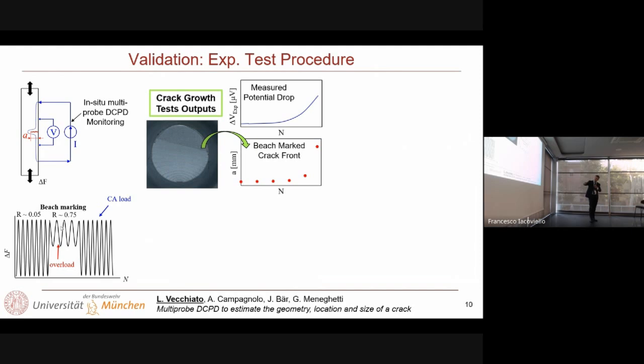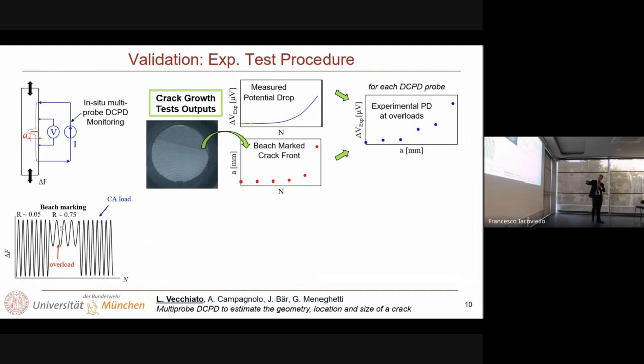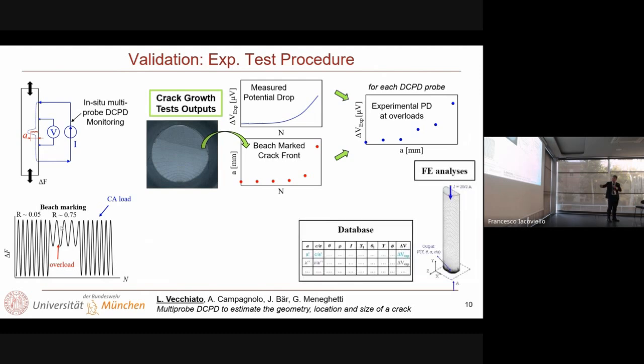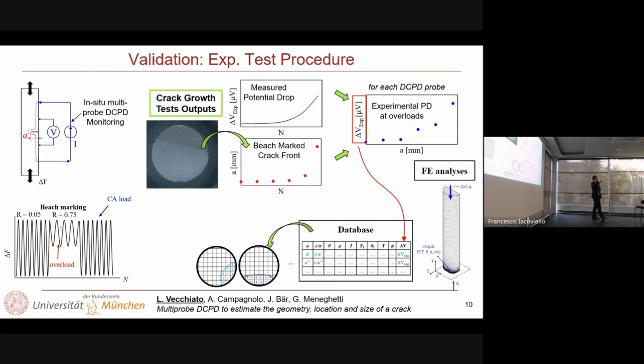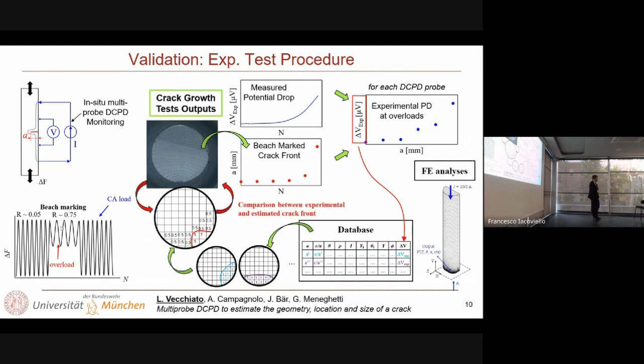And here you can see an example. At the same time, thanks to the fatigue testing, we have measured the potential drop, and for each marked crack front, we could measure the real experimental value of the potential drop. At the same time, we performed some finite element simulations and then entered the experimental value of the measured potential drop into our database and found all admissible configurations and generated for each one a corresponding picture, as I showed to you before.